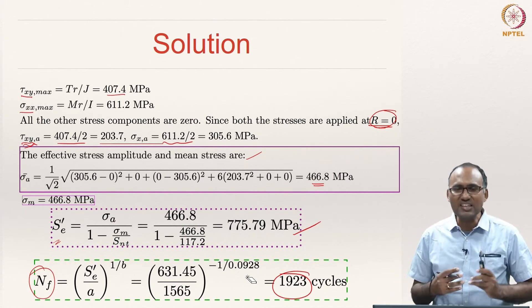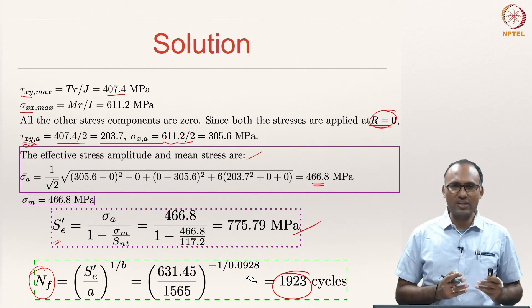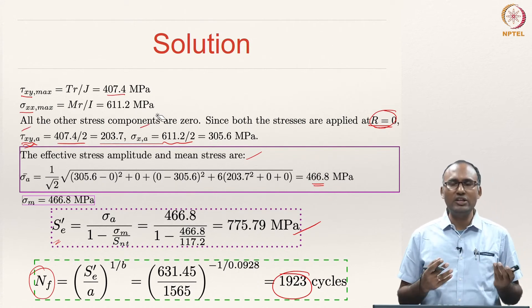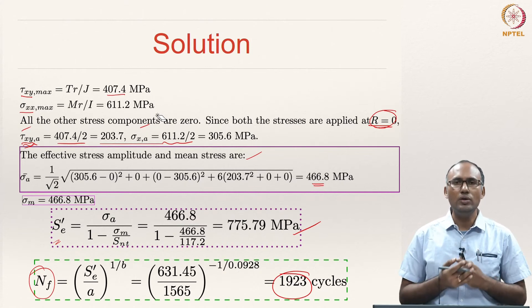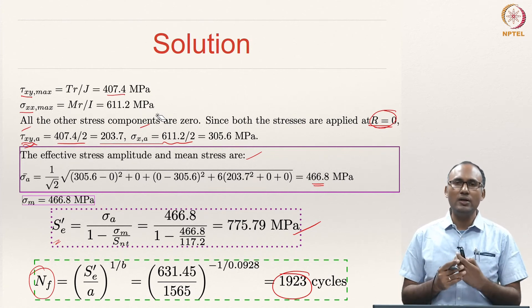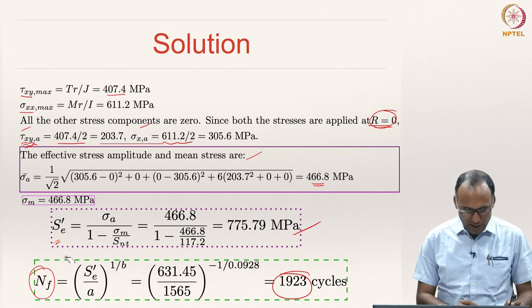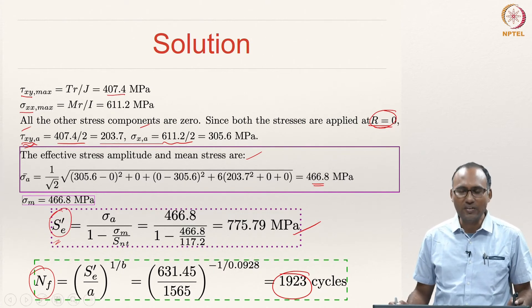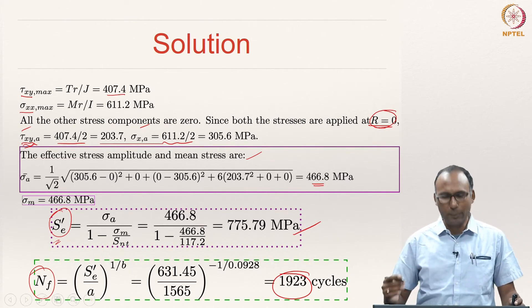The procedure is exactly the same except that instead of having one stress amplitude, you have two: one in shear and one in normal. All that we need to do is calculate the effective stress amplitude and similarly effective mean stress, then use those in the Goodman formula to calculate the fatigue strength, and from that fatigue strength calculate the life from the power law relation between stress amplitude and number of cycles to failure.